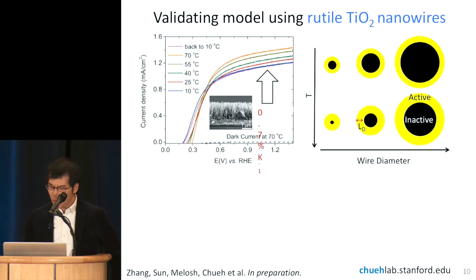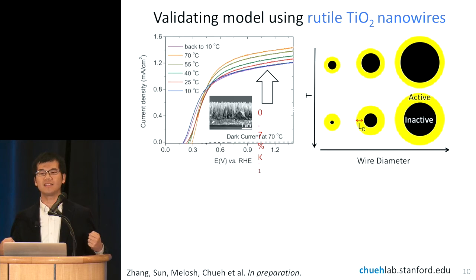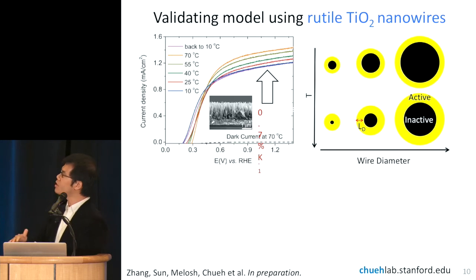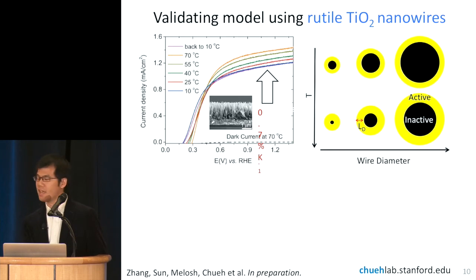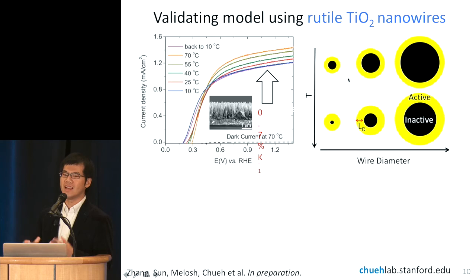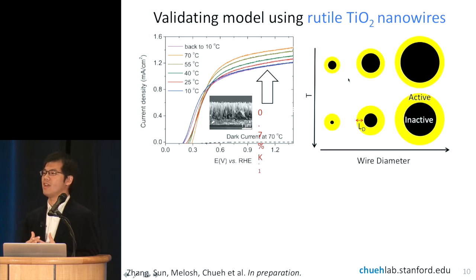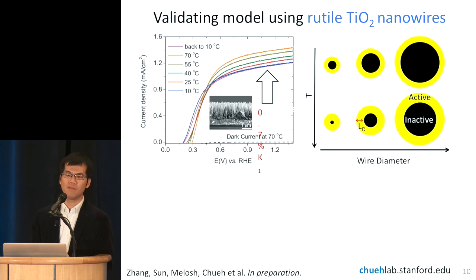And what we have done here is to use the controllability of the synthesis by varying the diameter of the wire. As you increase the diameter of the wire, the region which is occupied by the minority carrier diffusion length is actually getting smaller and smaller. As you increase the temperature for the smaller wires, eventually you'll run out of enhancement because you would have eventually activated the entire wire by increasing the minority carrier diffusion length. But for the larger wire, you will tend to still have a very much inactive core.